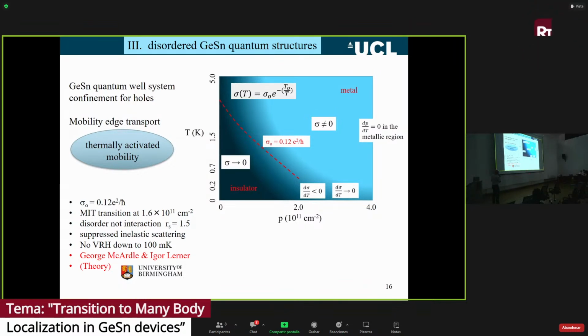We also get some other details. Sometimes the conductivity increases as we're decreasing the temperature, so d sigma by dT is negative. Sometimes d sigma by dT goes to 0. So in some of these regions, not very much happens. Just to summarize this, I've called it a metal-insulator transition, but it's already in the localized insulating regime.